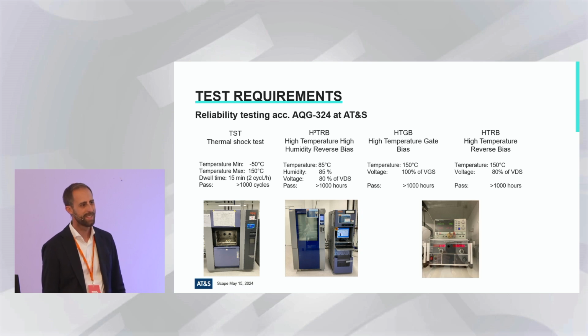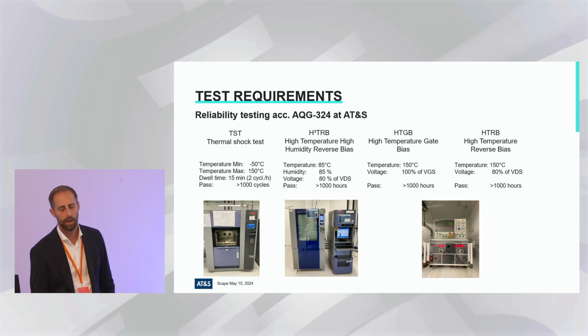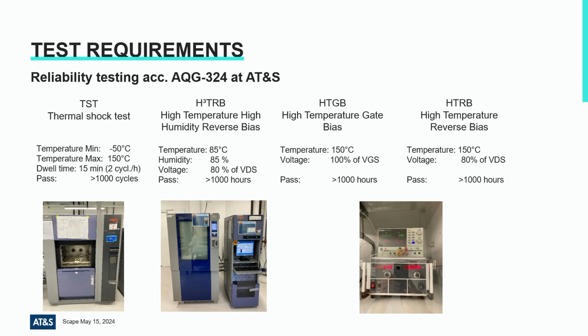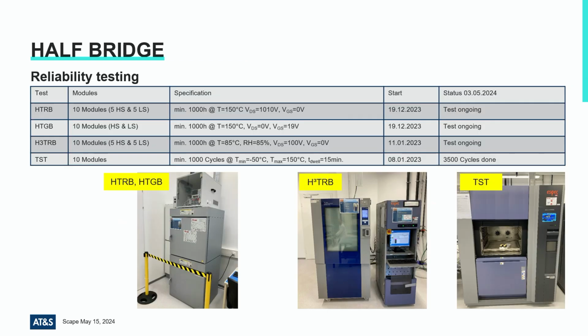Reliability. That's now the key element. And everyone is already laughing. As already mentioned as well, power cycling is not one of the critical tests. The critical test for this type of modules is humidity, temperature. And the voltage for sure. So that's the key elements. So we have these standard tests in-house. We also did already tests. The tests are also ongoing. We are now somewhere between 3,000 to 4,000 cycles, and we see quite good test results.